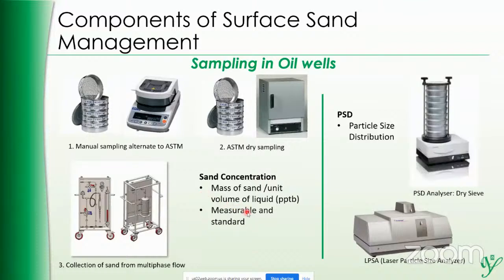What are the ways through which we can measure that? First, manual sampling. You can manually take samples, heat the sample so that all the liquid is gone, then measure how much sand is coming, and convert it into PPTB. There's a stationary lab mechanism as well, where you separate the sand along a sieve, take this filter and put it in an oven, and get all the liquid out. Then you measure the dry sand, and suppose you have collected it from a 5 liter bottle, you can convert that into PPTB.